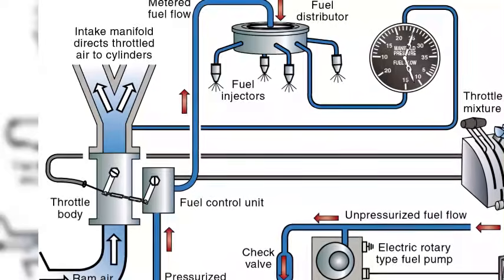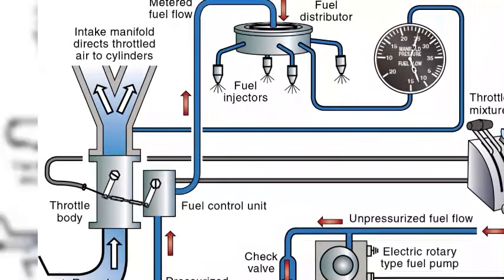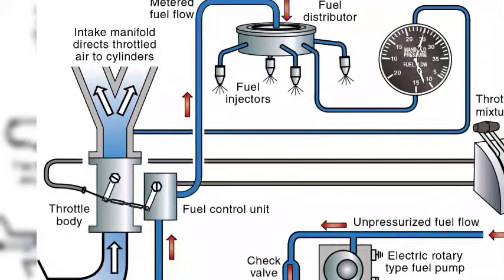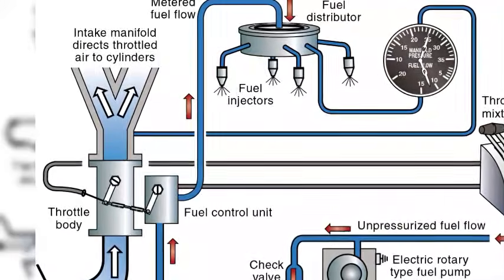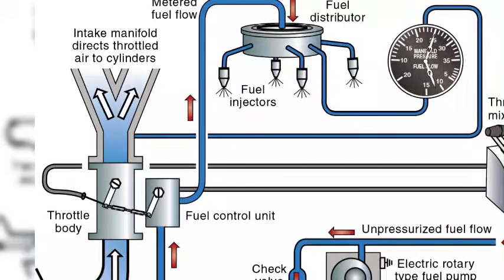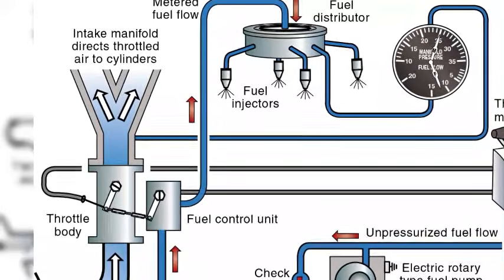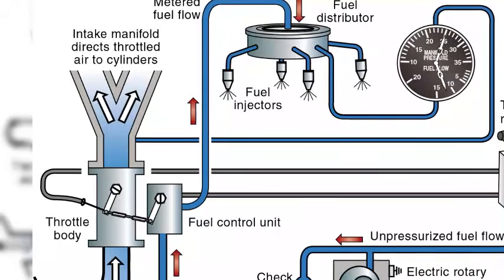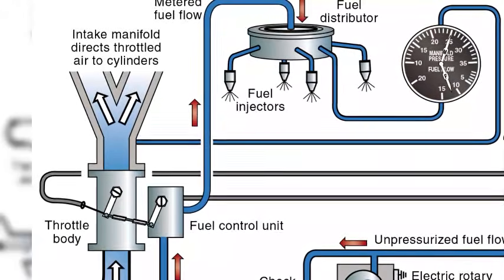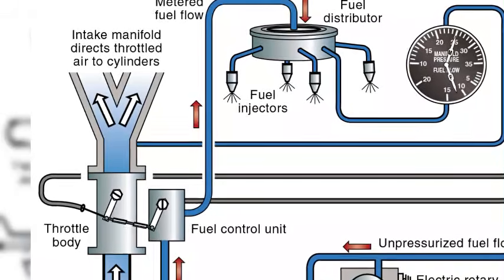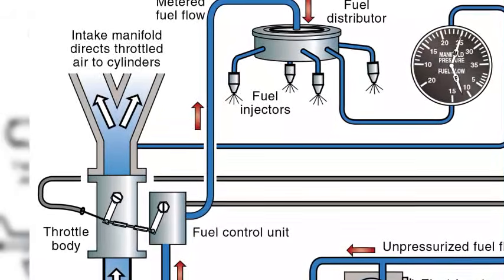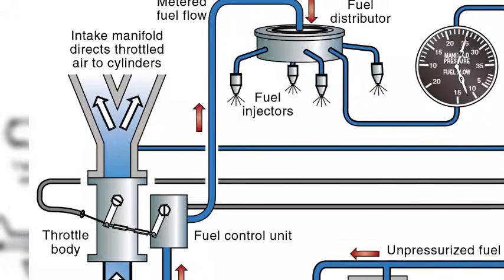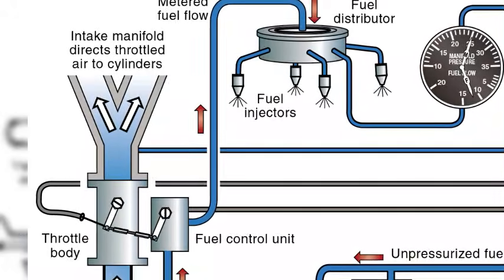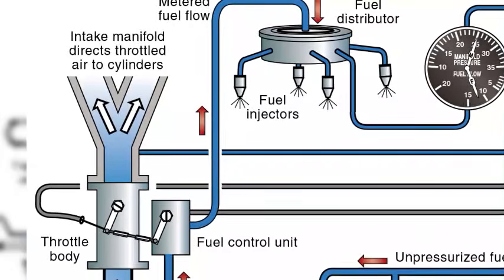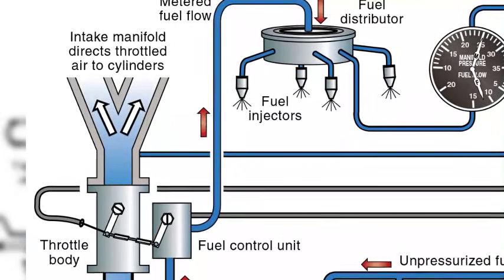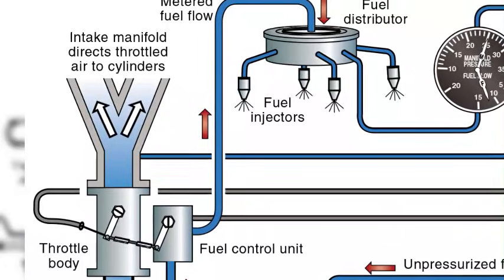The carburetor did not distribute the fuel evenly, so some cylinders ran richer than others, creating hot spots and contributing to both the overheating and the fouling problems. Some cylinders got too much fuel, ran rich, and fouled their plugs, while others got too little. The solution was direct fuel injection, which delivered a precisely metered amount of fuel to each cylinder individually, ensuring an even distribution. Fuel injection improved the cooling by evening out the combustion, and it reduced the spark plug fouling by ensuring that no cylinder ran excessively rich.